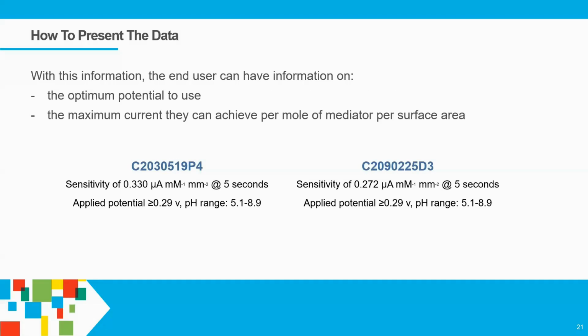And how we can actually represent the data. So in the previous slides, we gave them the actual working area measurements. So we can actually present the sensitivity in microamps per millimolar of the mediator at 5 seconds per millimeter squared. So they have a set design, they have different working electrode sizes. They can predict or get a good estimate of what kind of signal they will get. We also give applied potential, a minimum applied potential for the oxidative, maximum for the reductive.